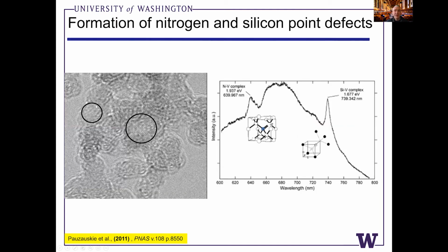We can also zoom in to look at the TEM of this material, and you can see these characteristic lattice fringes. These index to 111 d-spacings. I apologize that the scale bar somehow escaped this image. This is about a 2 nanometer grain. This is about a 4 nanometer grain. These are very small grain sizes that have this sort of reconstructed surface.